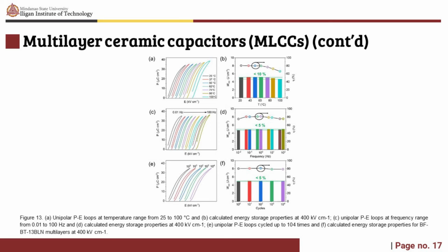The unipolar PE loops and energy storage properties are shown in Figure 13. Recoverable density is temperature stable from 25 to 100 degrees Celsius, with little variation as a function of frequency from 0.01 to 100 Hz, and cyclic loading up to 10^4, or 10,000, times.